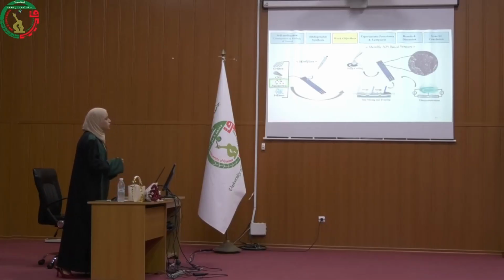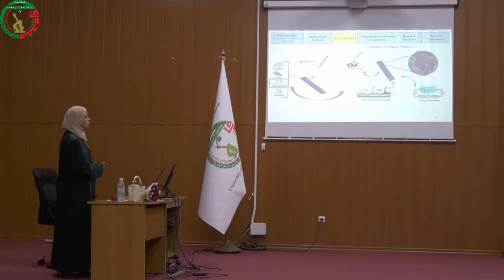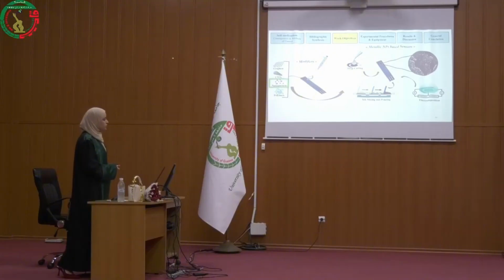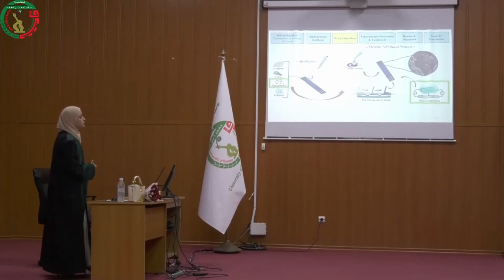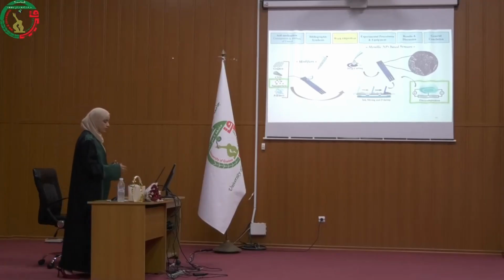The modification of screen-printed electrodes with metallic nanoparticles is done via drop casting, electrodeposition, or ink mixing. We selected electrodeposition, the most common method, because it offers precise control over nanoparticle morphology.